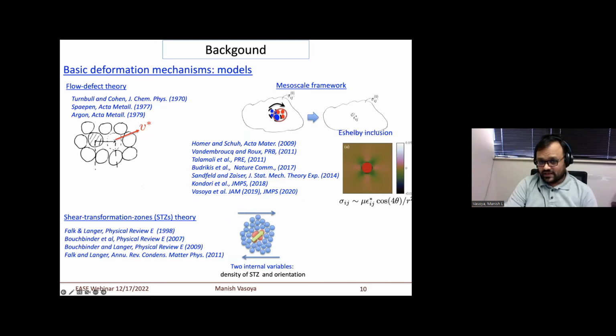So what models are available for modeling this deformation? They start with the flow defect theory, where the assumption was that because of this disorder you may also have free volumes. At some atoms nearby there is a free volume V star, which is the internal variable. When you impose load, that atom can move in that free volume and hence induce the local inelastic deformation. And there has been the mesoscale framework using the Eshelby inclusion. When that STZ happens, instead of tracking all the local atoms, you approximate that region as an inclusion and approximate that deformation as an eigenstrain. Then you solve the Eshelby solution to solve the problem. There have been many models on this work.